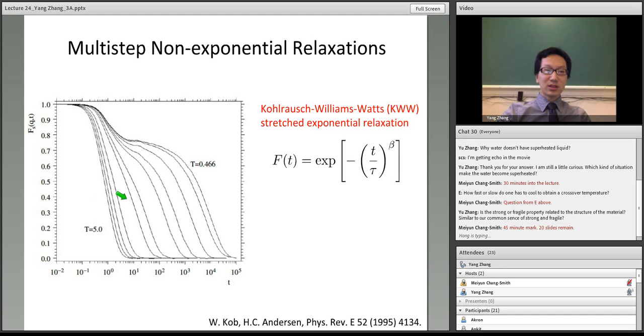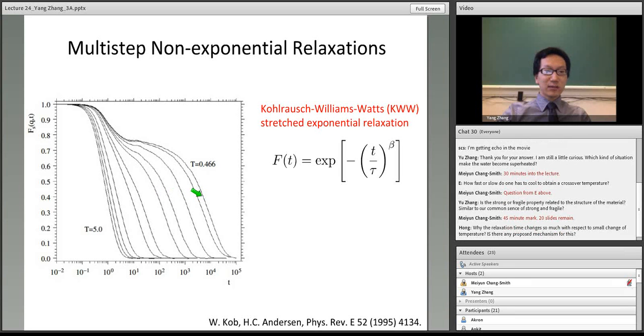When the temperature is lowered, you can see the relaxation time becomes longer and longer. Not only that, the relaxation becomes non-exponential, and there could be multi-step relaxations. This is also a very striking phenomenon observed for glass-forming liquids from neutron scattering, from light scattering, including X-ray scattering.